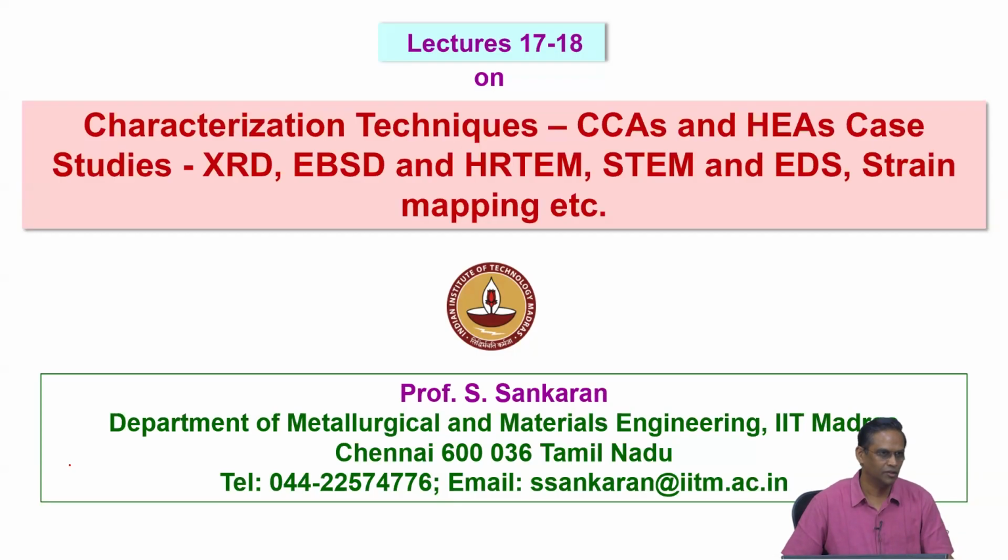We will not be able to identify the elemental distribution or the short range order. You should have a significant difference in atomic scattering factor between the elements, then your characterization techniques can identify them. Okay, so that is where we need techniques like neutron scattering or